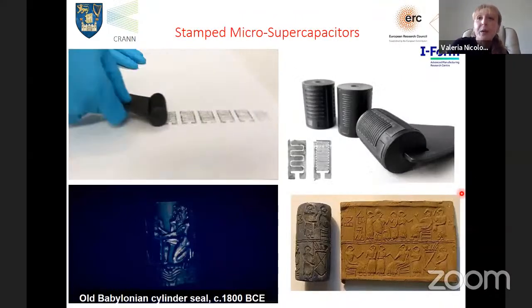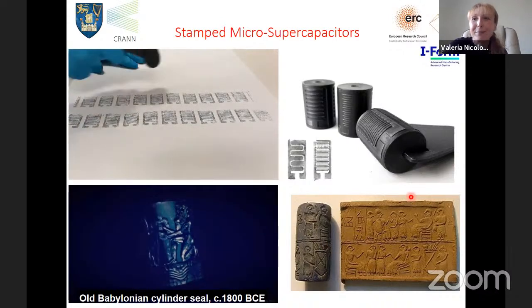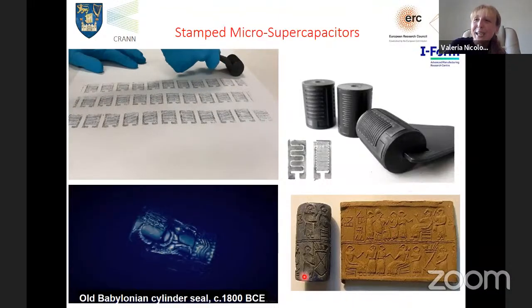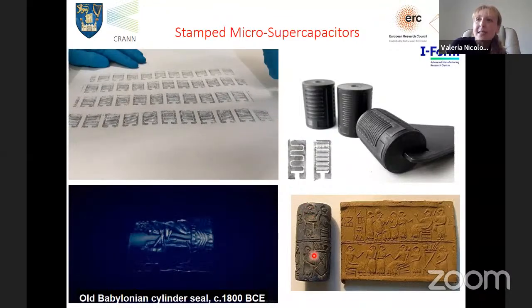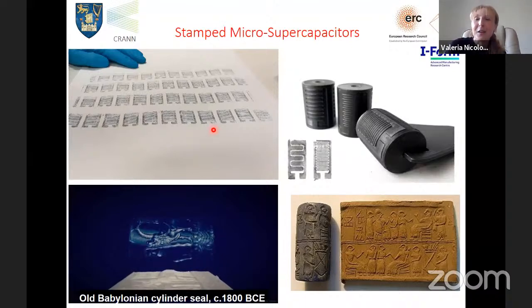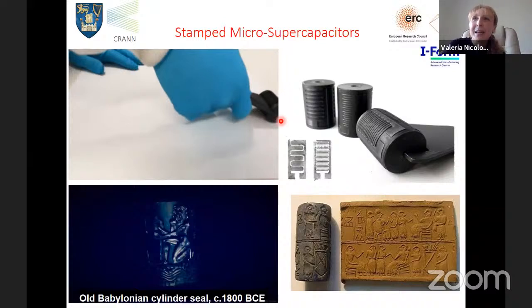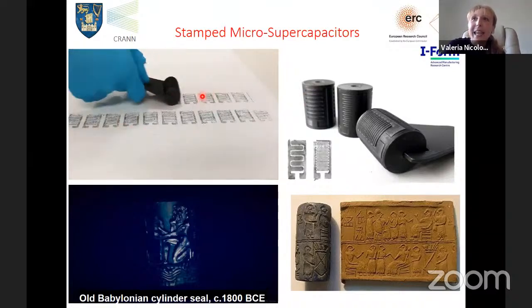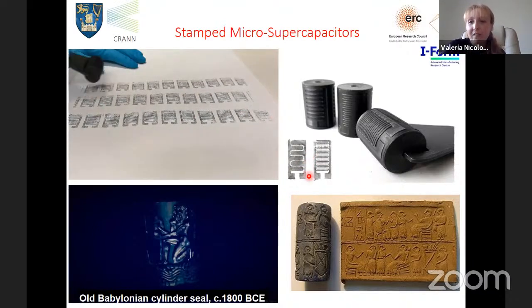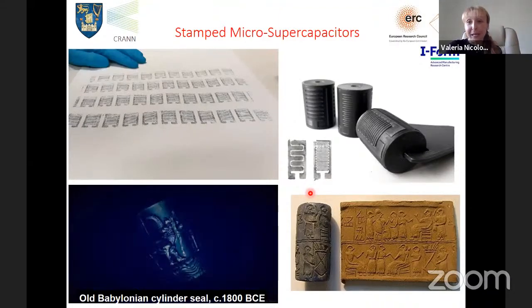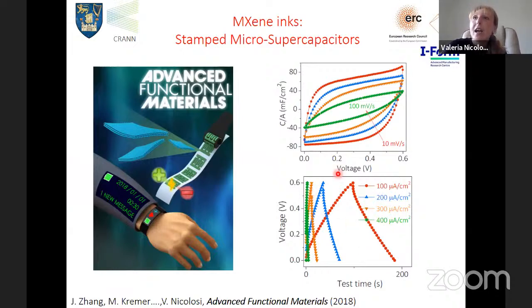Well, we also used the same concept. We used exactly what the Babylonians did back in the 18th century before Christ, where they were manufacturing these beautiful pieces of art. They were inscribing their rolls and then using them to create their art in a fast way. This is exactly what we did in our case. We printed these rolls by fused deposition method, and then loaded the ink inside, and there you go. Within seconds, you could manufacture and rapid prototype devices to test in a faster way, not possible otherwise. And these devices do indeed work. Again, beautiful electrochemical behavior, very high areal capacitance, up to high scan rates. Again, we can get up to 100 millivolts per second. Yes, you get resistive behavior at that stage, but below 50 millivolts per second, you have a nice and square